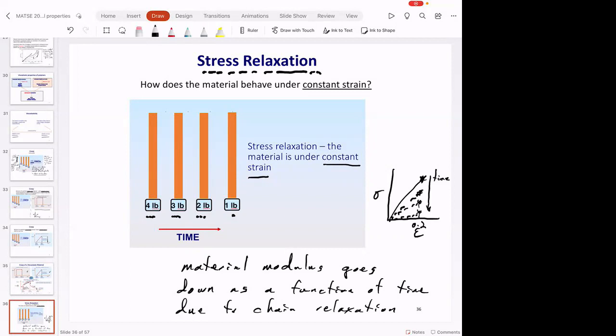So relaxation has to do with chain motion, right? I'm a chain relaxing, I'm disentangling, I'm moving around other chains. Do stiff chains relax faster or slower than flexible chains? Slower. So that's why we have to think like chains, right? Anything that stiffens the chain, cross-linking, higher Tg, crystallinity, physical cross-linking, those things slow down chain relaxation. So it's going to slow down stress relaxation and slow down creep.